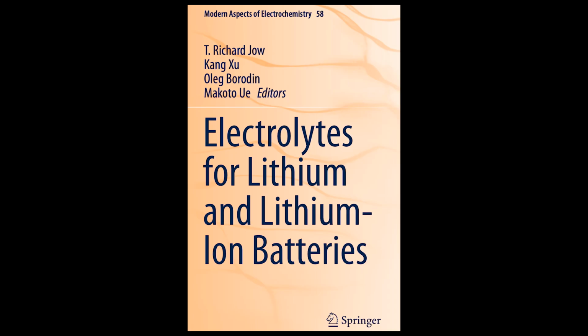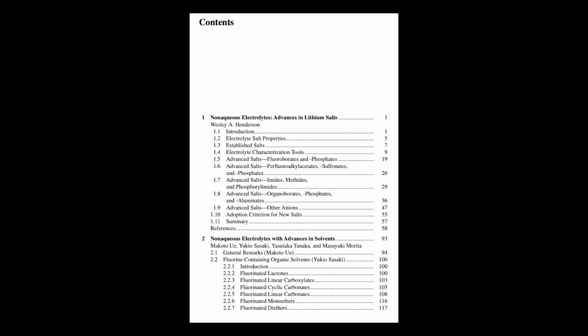Right. It turns out that you need a significant amount of TMP. The chapter mentions at least 20% by volume to achieve non-flammability. Figure 2.28 shows that while adding TMP can slightly decrease the ionic conductivity, it slows the ions down a bit. A little, yeah. But it still remains at reasonably high levels. And figure 2.29 provides an interesting result, showing that even in these TMP-containing gel electrolytes, adding vinylene carbonate, VC, remember the name? Yeah, the SEI former from earlier. Exactly. Adding VC as an SEI modifier helps maintain good performance of graphite electrodes over many charge-discharge cycles, even comparing favorably to traditional liquid electrolytes. So you get safety and decent performance.